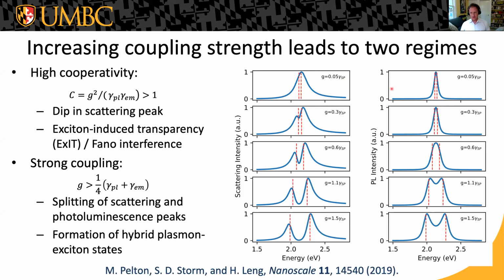And we go from, let's say, having the same photoluminescence and scattering spectra of the isolated metal nanostructure and quantum dot, to the strong coupling regime where we're forming polaritons. In both the scattering and the luminescence spectra, the peaks represent the splitting into these hybrid polaritonic modes. And this strong coupling criterion, well, within some factors of 2 that you may or may not agree with, tells you when you are forming these hybrid modes, when you get Rabi oscillations that coherently transfer energy back and forth between the exciton and the plasmon.